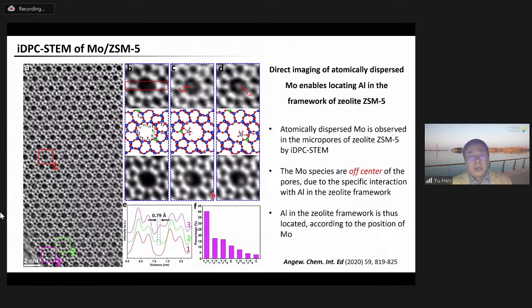So we used iDPC-STEM to image molybdenum atoms in zeolite channels. And based on the position of these molybdenum atoms and their specific interaction with the framework aluminum, we can locate the aluminum atoms in the zeolite framework. This cannot be done by other techniques.